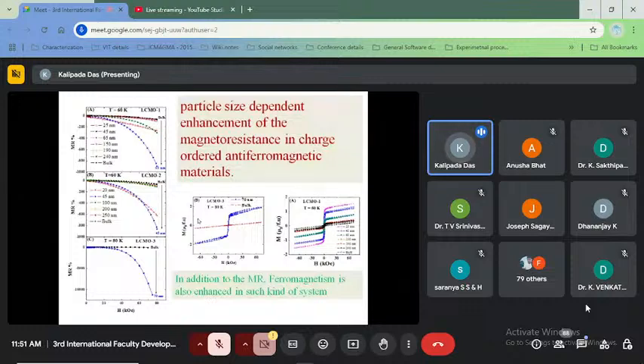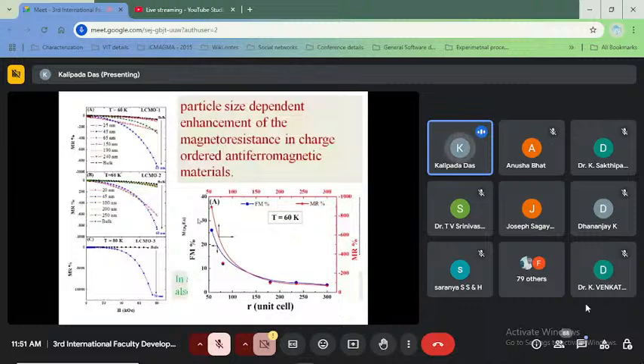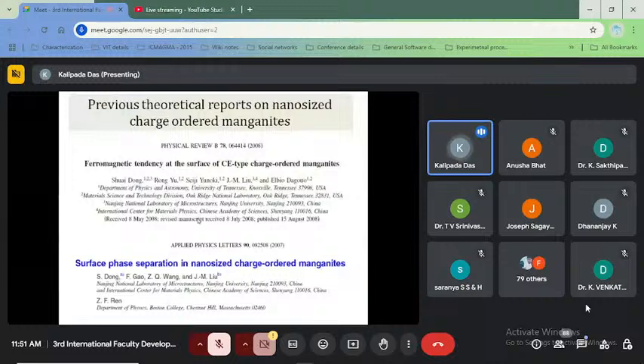So the underlying phenomenon is that the magnetic ground state changes with respect to the particle size. And from the experimental data, we see that the ferromagnetism gets enhanced as well as the magnetoresistance gets enhanced in a similar fashion with respect to particle size. Now, there are some previous reports on this phenomenon. Professor Dong already published that a ferromagnetic tendency appears at the surface of CE-type charge ordered manganites, and they also gave some insight on the surface phase separation in nano-sized charge ordered manganite.